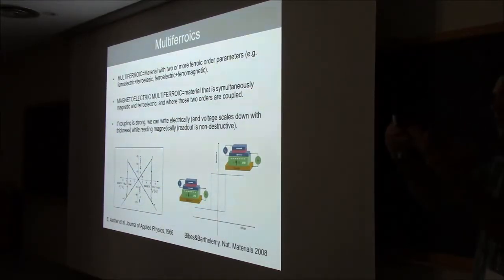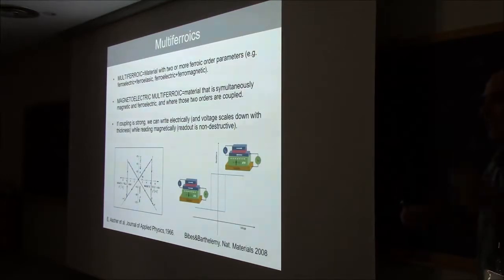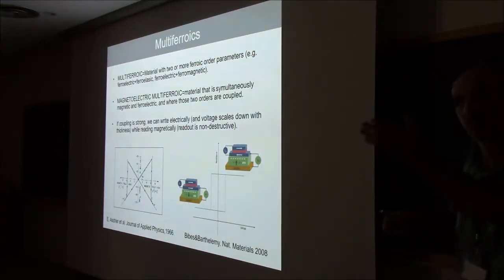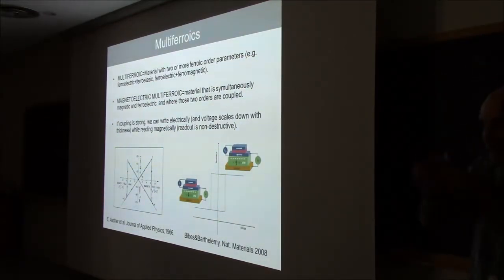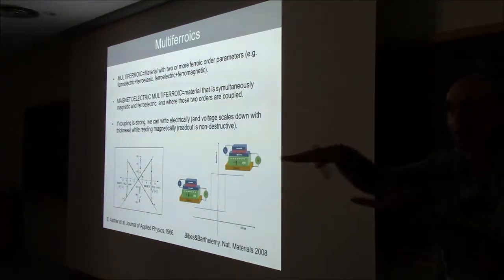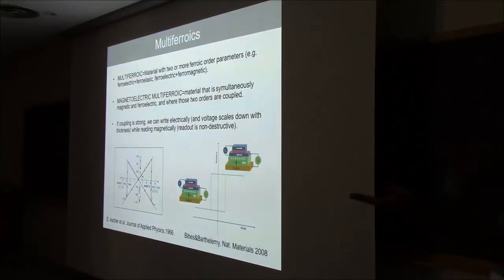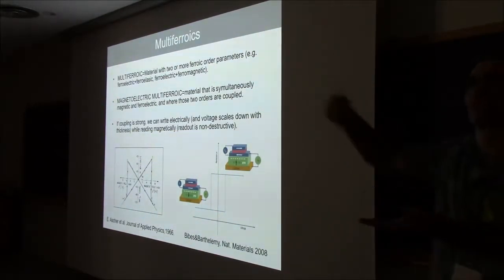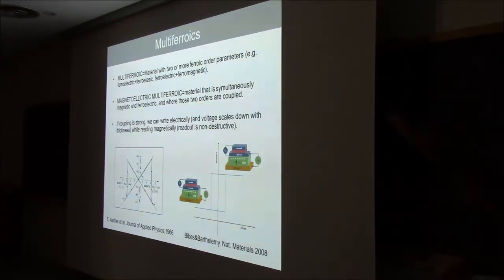That sounds very complicated, but basically what it means is that if you look at lanthanum aluminate, for example, maybe you're familiar with this substrate, you will see that it has these funky twins because it can shear in one direction or it can shear in the other direction, and between these 2 shearing directions there is an energy barrier. Okay, so if you measure the elastic response, it's hysteretic. That's a ferroelastic. So you can have ferroelectric ferroelastics, and you can have ferroelectric ferromagnetics, and you can have all combinations of this. The one that people are excited about is the combination of ferroelectricity and magnetism in the same